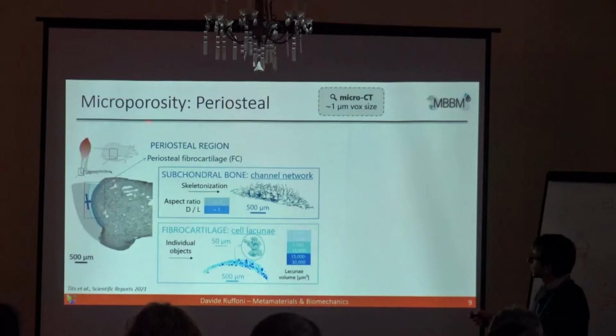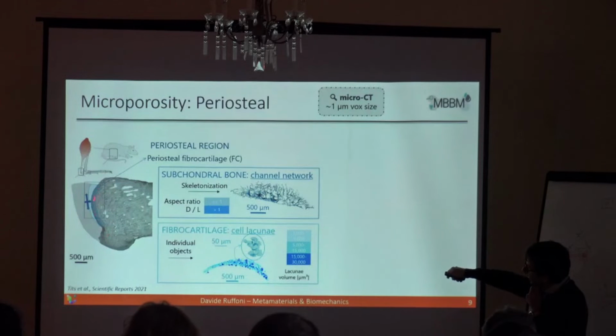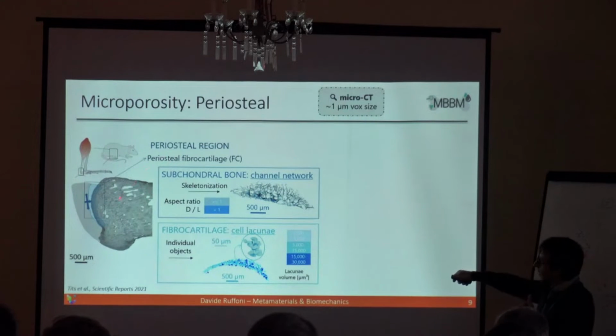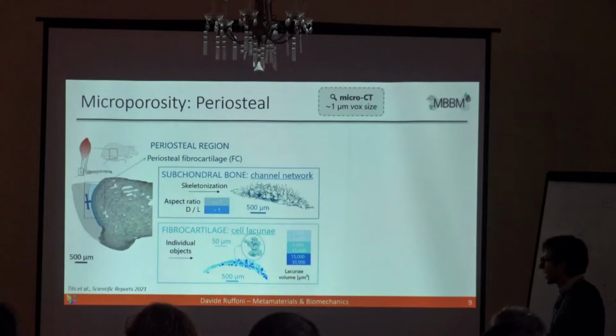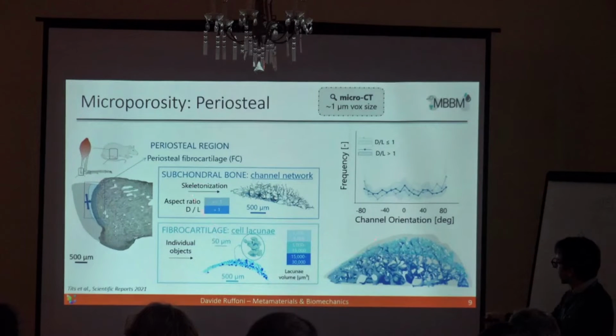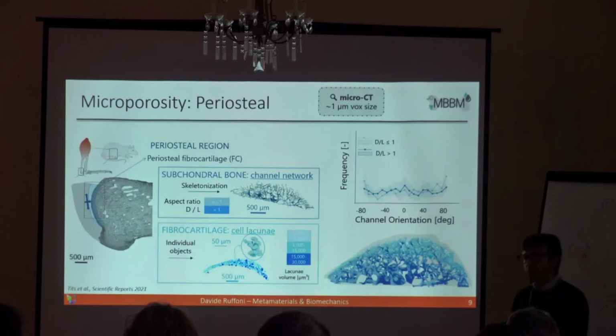Well, in terms of microporosity, we did some microcomputed tomography, so high resolution X-ray analysis, and we focused first of all on this region where we see this periosteal fibrocartilage. This was the fibrocartilage which has to accommodate sliding between the two tissues. And what we saw is that there are some pores to accommodate the blood vessels, and also some other pores to accommodate cells. So these are once again pores inside the highly mineralized matrix. If we investigate the distribution of those pores, the anisotropy, the orientation, we see no preferential orientation here. So it's an isotropic porosity, so to say.